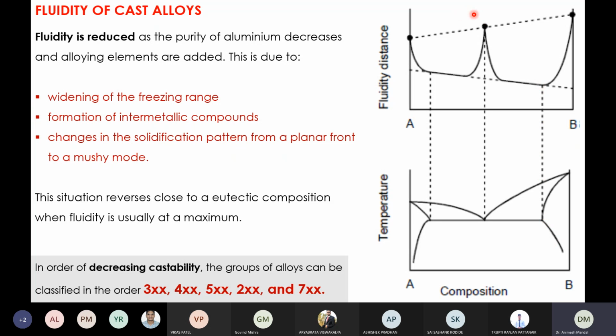So what it shows is that the eutectic composition has the best fluidity. In fact, it has the highest fluidity amongst all the compositions. Now the reason for this is that this particular composition has 100% eutectic, right? It is 100% because this is a eutectic composition, and it is the lowest melting phase. So, lowest melting eutectic mixture.